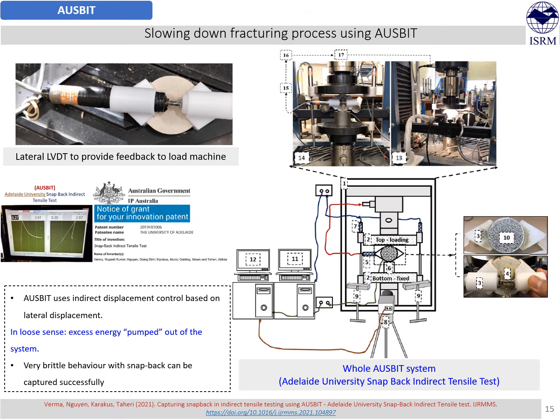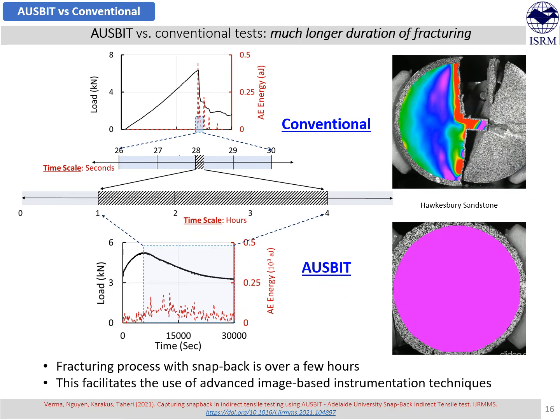That means if the lateral deformation of the disk specimen increases, the AUSBIT experimentation, which uses servo control, tends to reduce the loading rate to ensure that the lateral deformation rate further reduces to our predefined level. And if the lateral deformation rate reduces below our predefined level, the vertical diametrical loading rate increases accordingly. By doing that, we were successful in prolonging the instant cracking of the disk specimen.